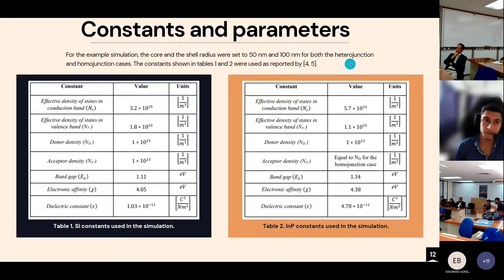Constants and parameters. For the example simulation, the core and the shell radius were set to 50 nanometers and 100 nanometers, respectively, for both the heterojunction and homojunction cases. The constants shown in tables 1 and 2 were used and reported in the literature.